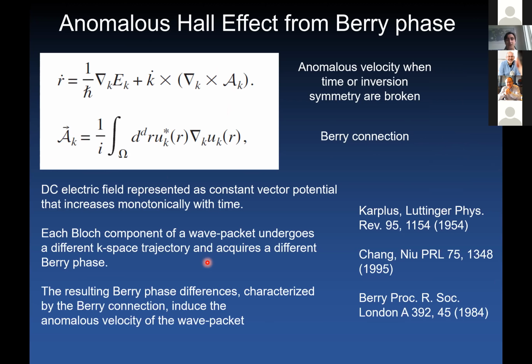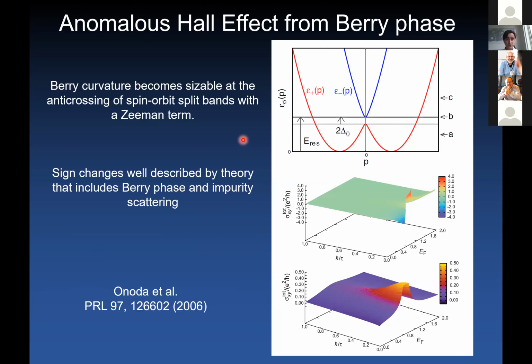So when you apply a DC electric field, you can represent this as a constant vector potential that increases monotonically with time. So this causes an evolution of a Bloch wave packet around configuration space, and each component will acquire a different Berry phase whenever the time or inversion symmetry are broken. So the resulting phase differences will sum up to give a certain Berry connection, which will be a source of the presence of effective electromagnetic fields in your system.